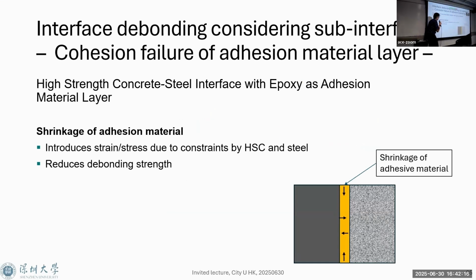Then even in this case, if both sides are very high strength, the debonding takes place within the adhesion material layer. In this case, usually this is a polymer. The polymer is confined, its shrinkage is restricted, so pre-stress is introduced within the material layer. This affects and reduces the bonding strength. So we have many other aspects as well.